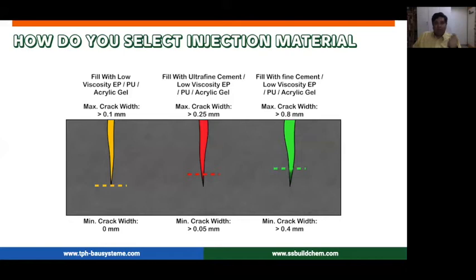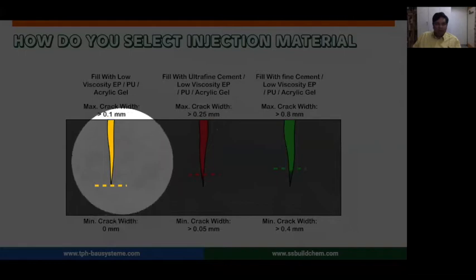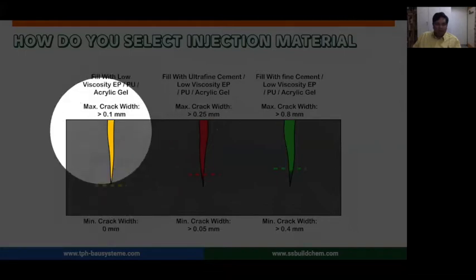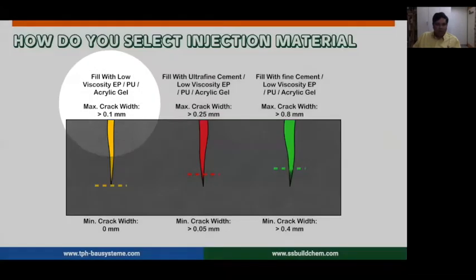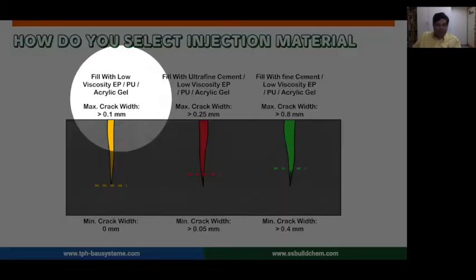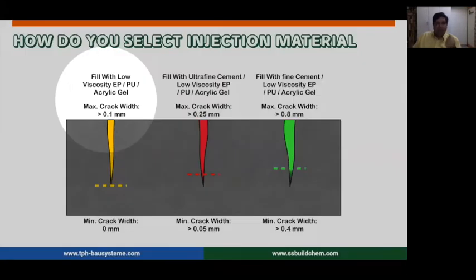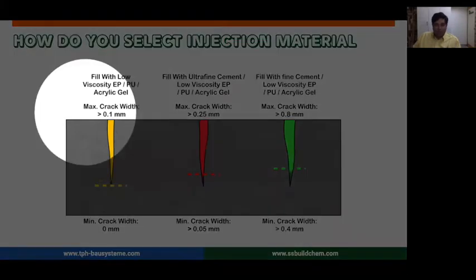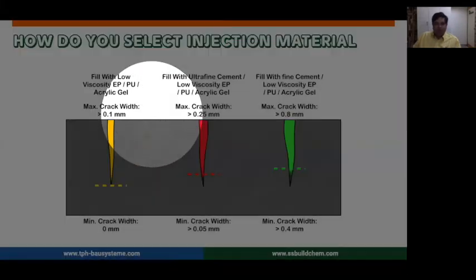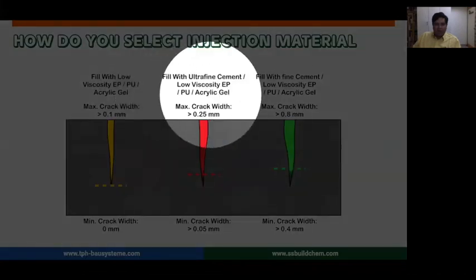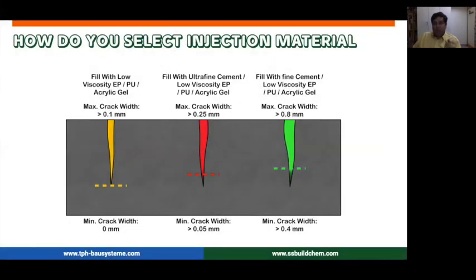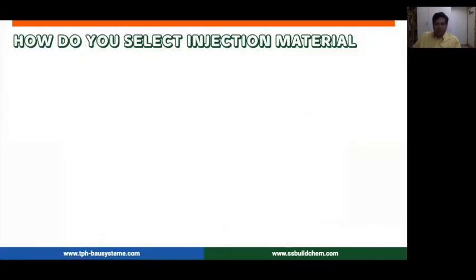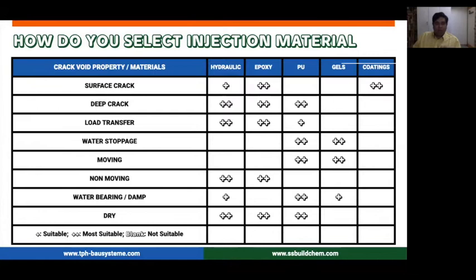And the selection of the injection material depends pretty much on your crack width. For example, if your crack width is maybe 0 to about 0.1, 0.2, 0.3 mm, then the only thing that can go inside would be a low viscosity EP, a PU, or an acrylic gel. In this kind of case, you can't go in with cement. If your crack widths are somewhere around 0.25, then you can start thinking about ultrafine cements. But only if your crack widths are more than say 0.8, 0.9, then you can start looking at cement grouting as an option.